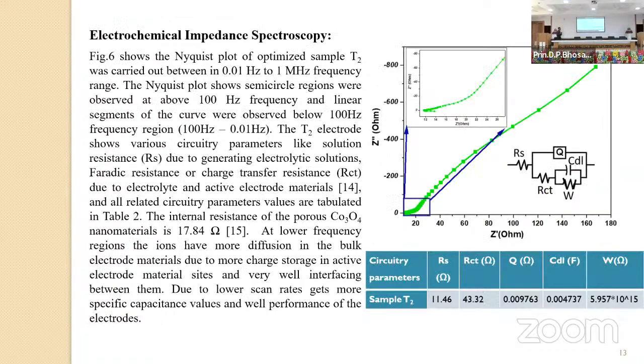Then last is EIS, electrochemical impedance spectroscopy. This is very important for the supercapacitor, another electrochemical analysis. This graph is of the optimized sample, that is the 10-minute deposition, and it shows the Nyquist plot. With the Nyquist plot, I can use a circuit diagram here.